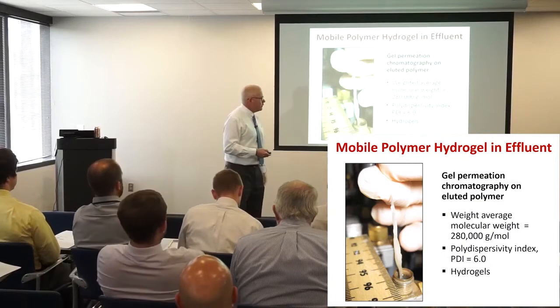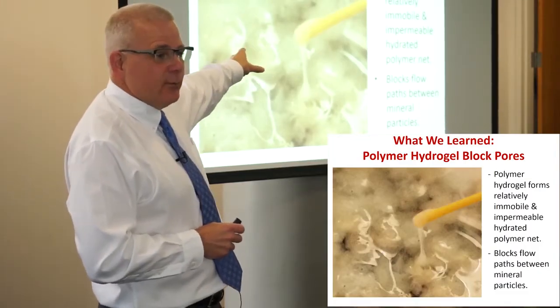These are kind of high molecular weight polymers that bind with water molecules. And what we found is they form a gel — a hydrogel. And imagine if you put that in the pore spaces of a bentonite. What happens? It clogs it up. It's a very simple phenomenon.